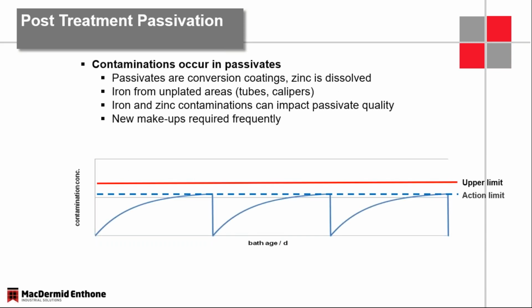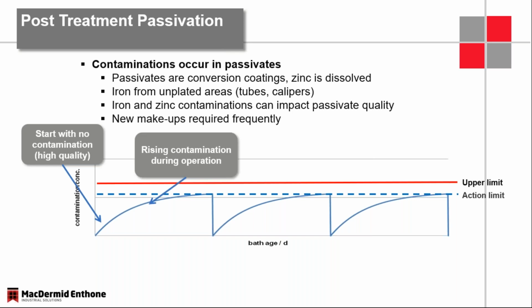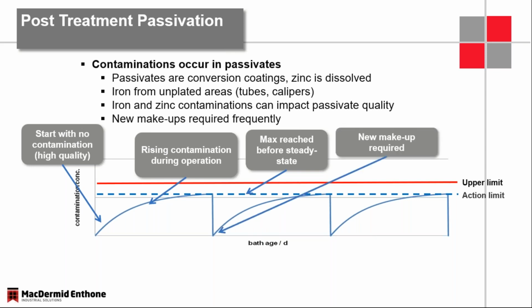So what does this mean? We're putting a zinc or zinc alloy part in a tank of passivate. We're forming the passivate solution. We're dissolving off zinc. That zinc contamination starts to rise, and then we start to reach our action limit, as I had mentioned, and then our upper limit. Unless you're doing a significant amount of barrel work, you might reach a steady state where you're dragging out as much of the zinc and iron as you're bringing in. But in most cases, you're not, and you have to put in a new makeup.